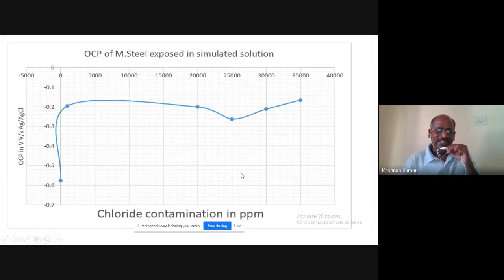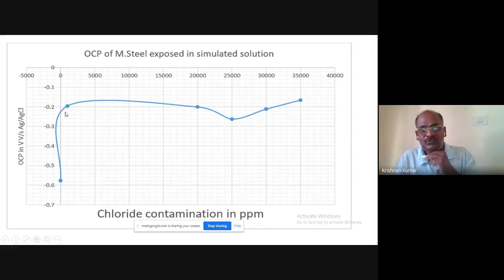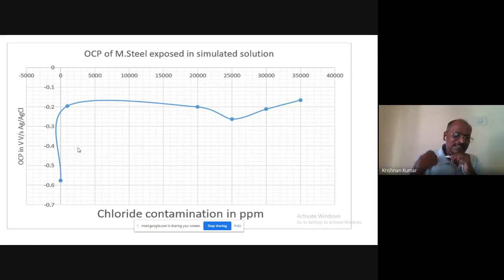You can see another very important thing, the open circuit potential. Before making the polarization, we took the open circuit potential with respect to the different contaminations. Initially, the open circuit potential is minus 0.6 volts. And immediately after 1000 ppm, it went to minus 0.2. What is the reason for this? Because chloride is a very good conductor. Because of the conductivity, it went to a higher potential.